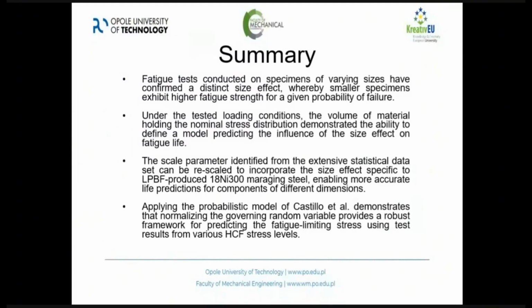So, going to the summary, the fatigue tests conducted on specimens of varying sizes have confirmed a distinct size effect, where smaller specimens exhibit higher fatigue strength for a given probability. Under the tested loading condition, the volume of material holding the nominal stress distribution demonstrated the ability to define a model predicting the influence of the size effect on the fatigue life. The scale parameter identified from the extensive statistical data set can be rescaled to incorporate the size effect. We tested it for this steel, so we can say only it worked for this steel at this moment, enabling more accurate predictions for different sizes and shapes maybe.